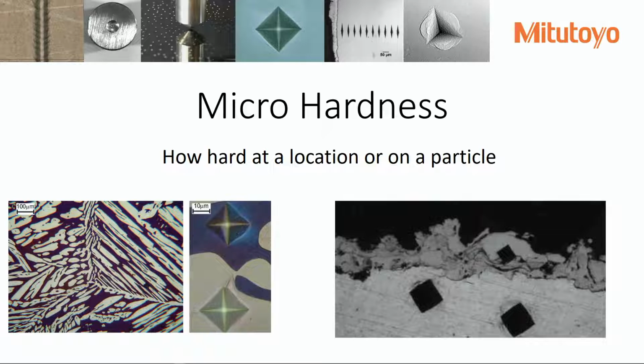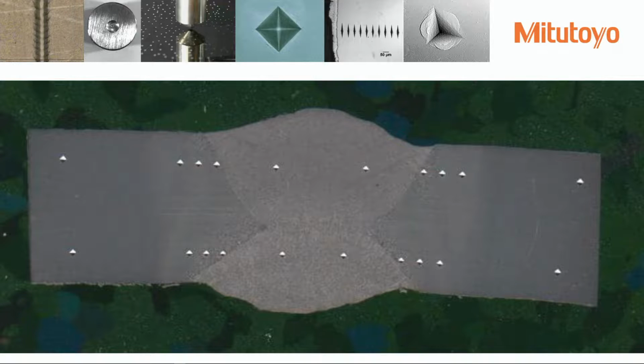The picture on the far right is a plasma spray coating. You can see easily the small indentation in the hard flame spray part, and the larger indentation is the softer. Or the middle picture, it's a 2-phase alloy, and you can check the hardness in the 2 different phases.